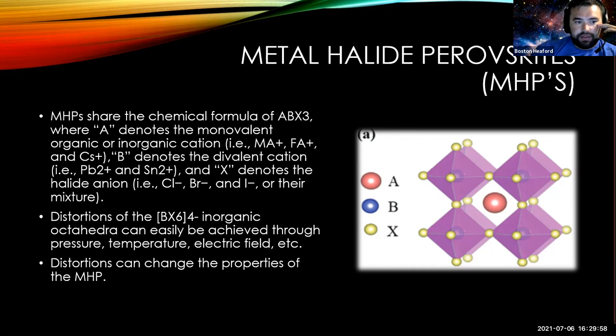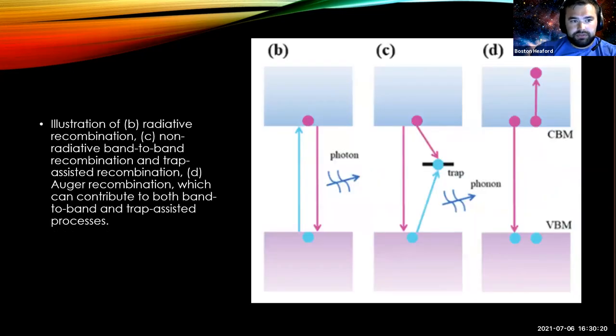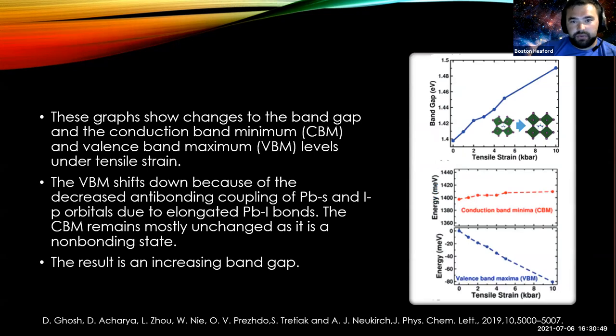In this structure, distortions can change the properties of the metal halide perovskite, from electrical properties to optical properties, things like that. This is also just another quick illustration of radiative recombination, non-radiative band-to-band recombination, and then D is Auger recombination. Just different processes where electrons and holes can recombine and stop being charge carriers, which is what we don't want to happen in the system. And so one of the things that can affect...